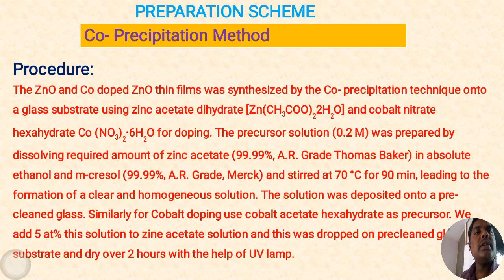Now, for that purpose, we use a simple co-precipitation method for preparation of zinc oxide film, with zinc acetate as the precursor, and for doping, cobalt nitrate hexahydrate. In the actual procedure, the 0.2 molar precursor solution was prepared by dissolving the required amount of zinc acetate in absolute ethanol and m-cresol and stirred at 70 degrees Celsius for 90 minutes, leading to the formation of a clear and homogeneous solution. The solution was deposited onto a pre-cleaned glass surface.